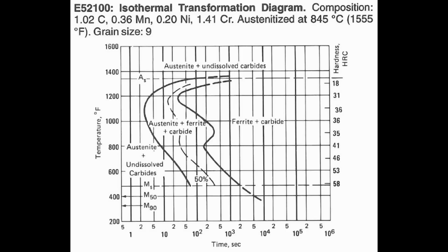So between the start and 50% is only about 250 seconds, because this is a log scale. Even though the 50% line looks halfway in between start and finish, the 50% is reached quite early on. Then the transformation slows with further time, and it takes up to 2,000 seconds, around 33 minutes, to be fully transformed. Then on the far right of the diagram, there are different hardness numbers. They're showing when they austempered right above martensite start at 500 degrees, they got about 58 Rockwell at the end.